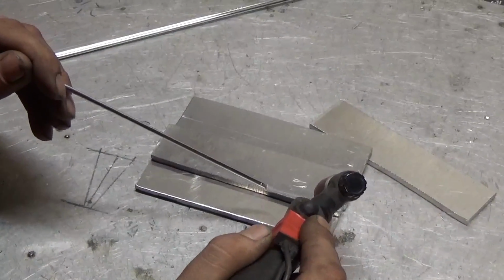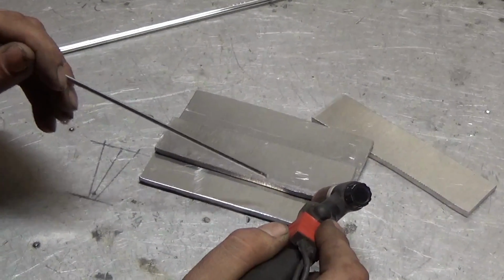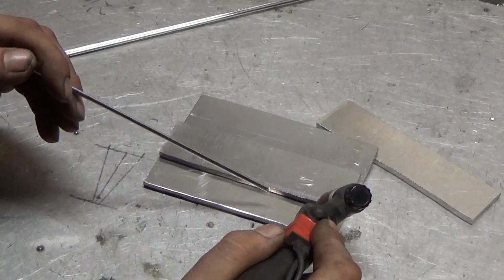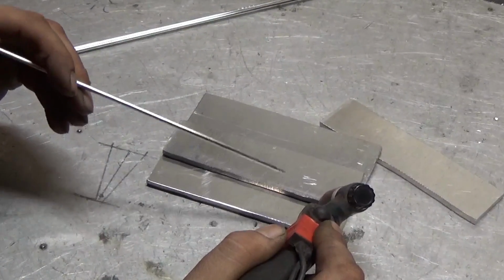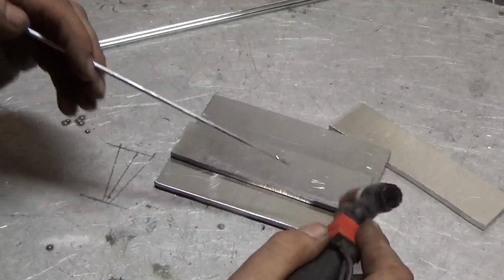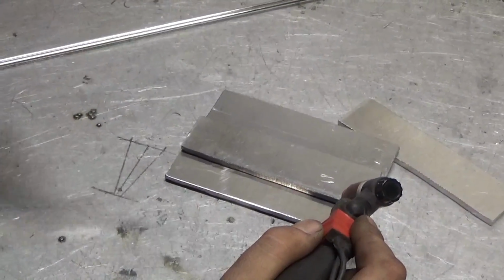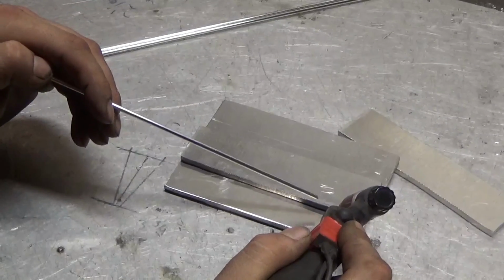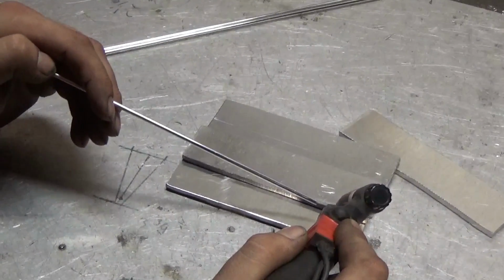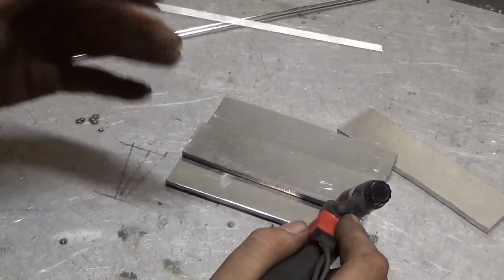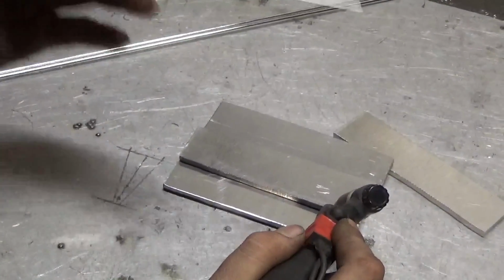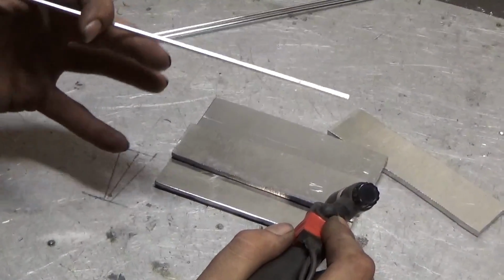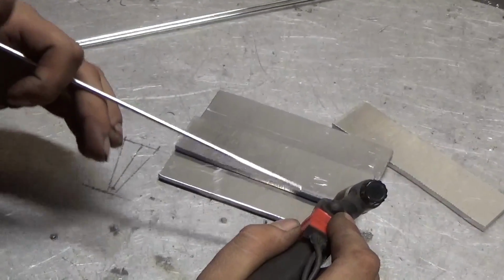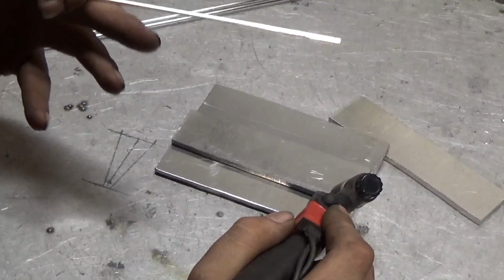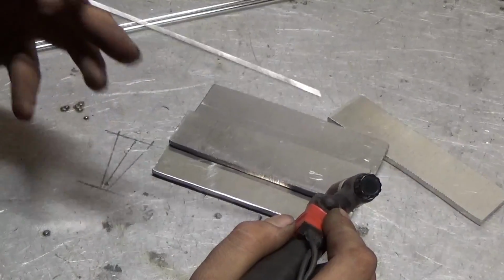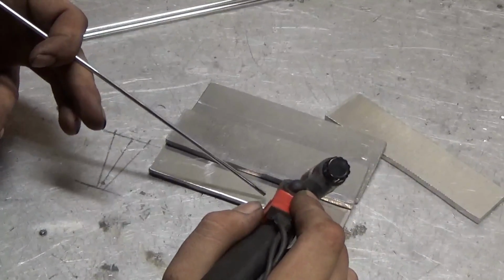Now the most important thing I find with aluminum that a lot of people mistake is they don't let the puddle wet out before they start adding wire or moving. And when that happens, what you'll get is you'll get the wire to start to ball up before it enters the puddle, or you'll just get a dirty weld, because the way that the AC welding works is it has to clean the metal before it does the penetration work. So if you don't sit there and let it wet in, the puddle will get a nice sheen to it. That's when you know you're ready to start adding wire and moving.